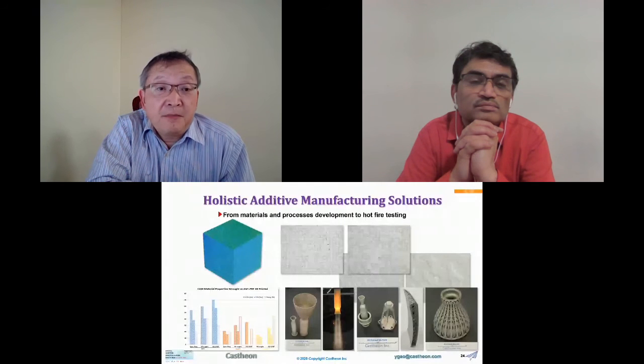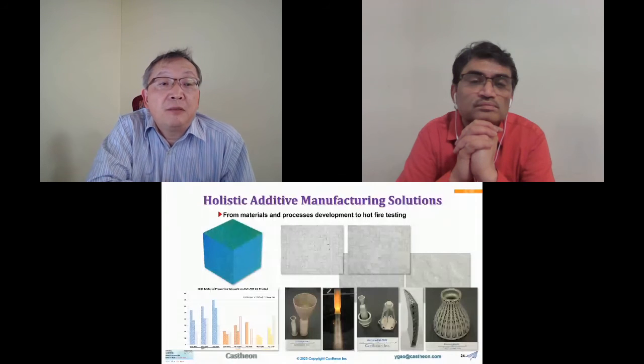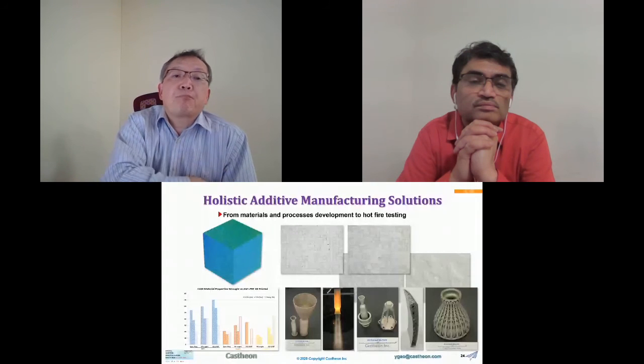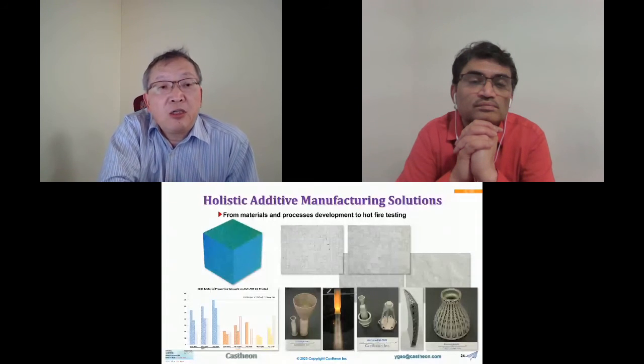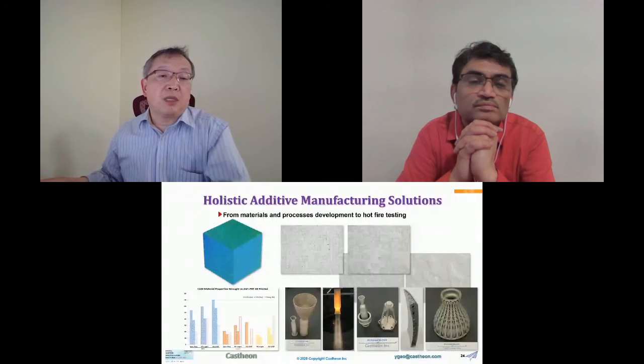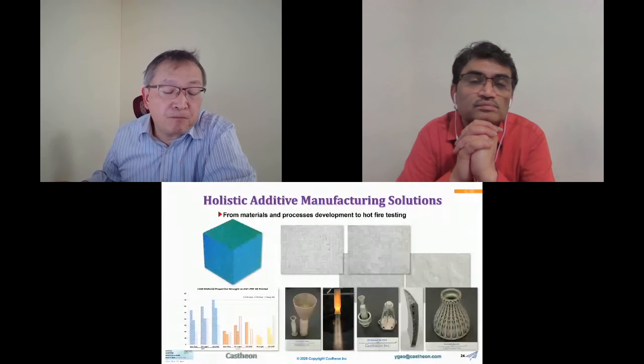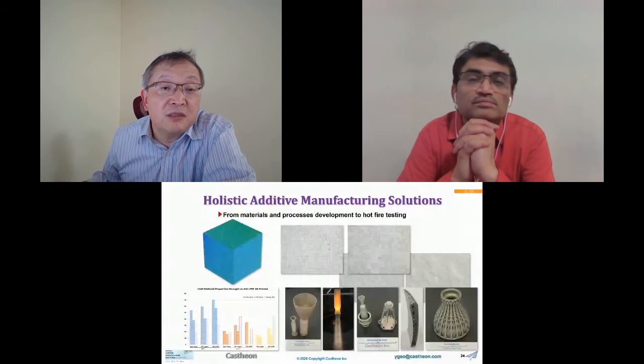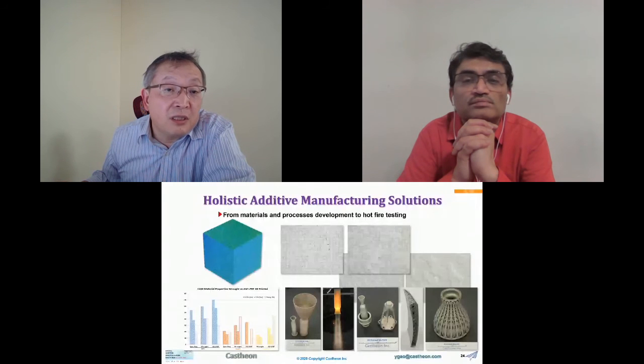And this is another example, the niobium C103. A couple of years ago, we developed this niobium C103, which is a refractory material. What we found was, the two pictures above on the metallography are the green structures of the 3D printed material. The difference is in the middle, the as-printed microstructure.